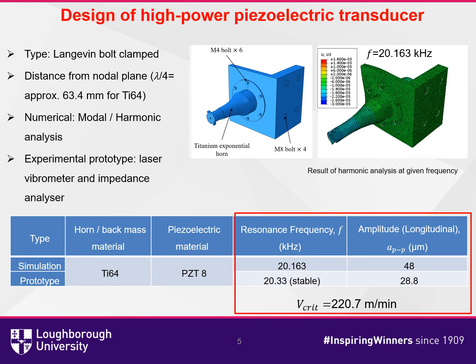The piezoelectric transducer is self-designed and manufactured for major vibration to be longitudinal along transducer axis. The design process includes λ/4 length from the nodal plane to provide maximum vibration at the transducer tip, where the tool is located. The simple case of lambda can be obtained by speed of sound of mass material over desired operating frequency. The whole design was validated by performing modal and harmonic analysis in the simulation.